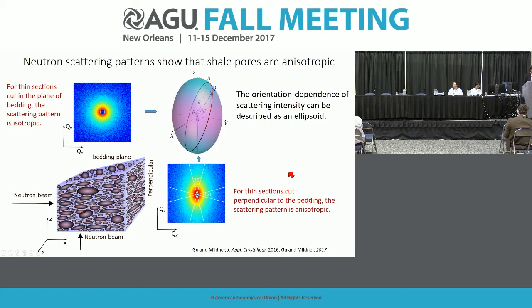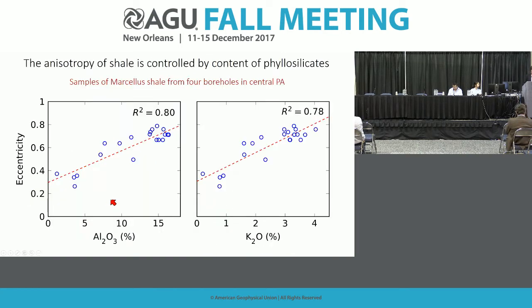When Jingu uses neutron scattering on shales and sends the neutrons through it, if the thin section is in the plane of bedding, you see isotropic scattering. If the thin section is perpendicular, you see anisotropic. And this is really, at heart, the explanation for the fissility of the shale. The eccentricity is one way to categorize anisotropy. And this anisotropy, this eccentricity, increases with the alumina content and with the potassium content.